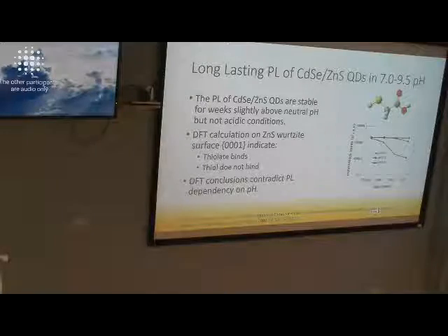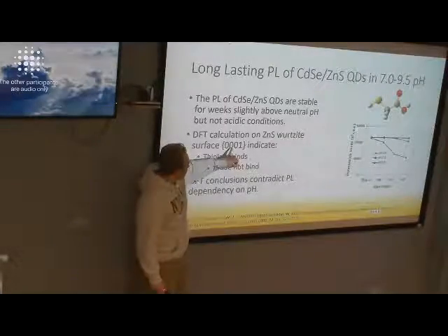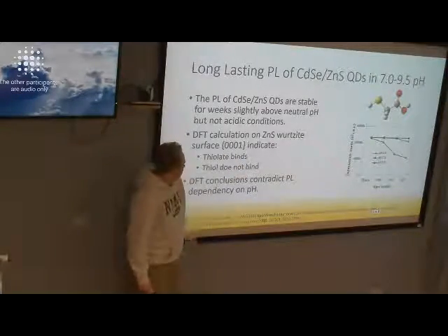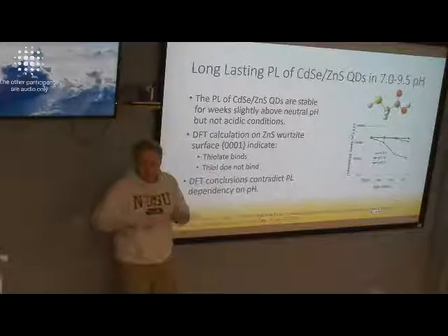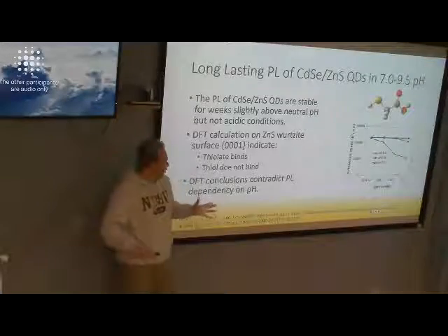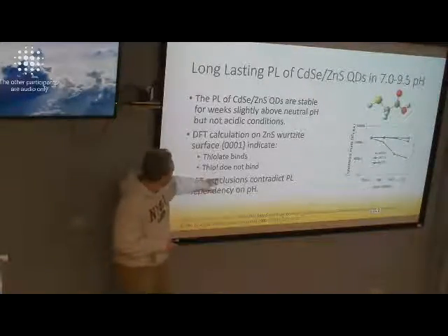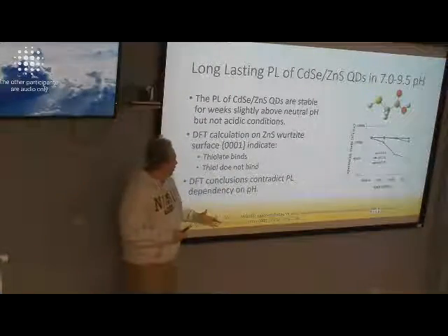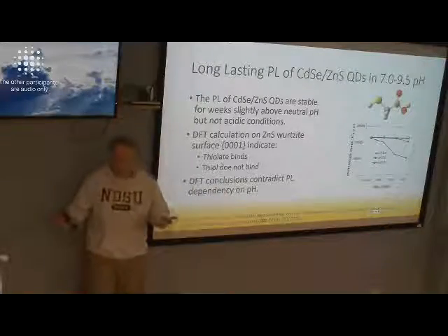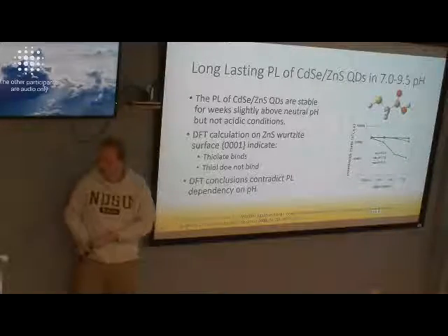Okay. So this paper said from DFT that thiolate binds to zinc sulfide wurtzite on the 001 surface. They did a slab of material instead of a sphere. Thiol does not bind. So here they say thiol does not bind, where before it looked like thiol did bind and had the best properties.